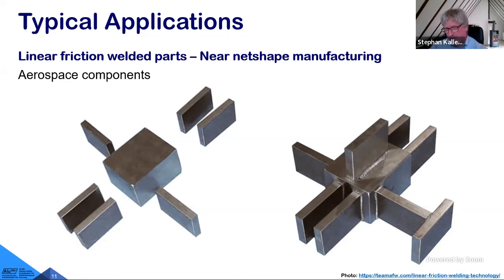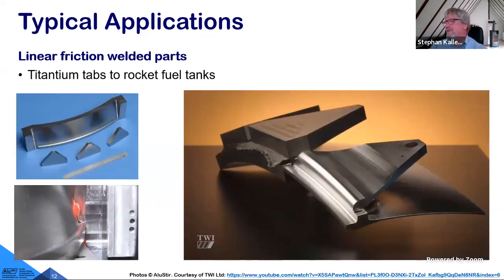Why do we need the high forces? In solid phase welding, we want to stay below the melting point of the material. And by that, it's more like a forging process. It's more like a process where you, like making this Damascene steel, the swords, forge welding, fire welding, where material just gets hot. And at the end of the cycle, and we come to that in a second, we will increase the pressure to get all this plasticized material pressed into the flash or burr.